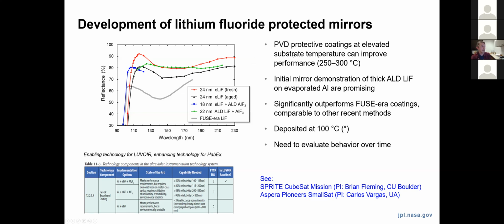There's been a lot of nice work, for example, out of Goddard Space Flight Center in developing evaporation processes for lithium fluoride that essentially are done at a high substrate temperature. And this has been seen to really improve the performance over these legacy coatings. So this red curve here is an example of what they call ELIF, or enhanced lithium fluoride. But even this high temperature lithium fluoride tends to degrade as a function of time.